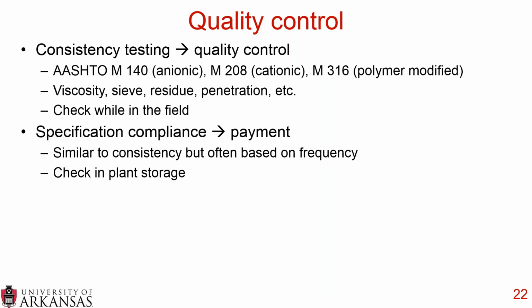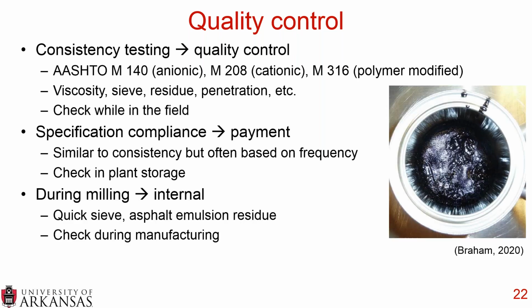Specification compliance is another important part of quality control, and this has to do with payment. It's very similar to consistency testing, but it's based on the frequency, and you want to check the material that's being stored in the plant. So ideally, you want to store material as minimally as possible in the plant. You don't want asphalt emulsion sitting in a tank for long periods of time, but you can do tests on that plant storage in order to make sure the product is behaving as it should.